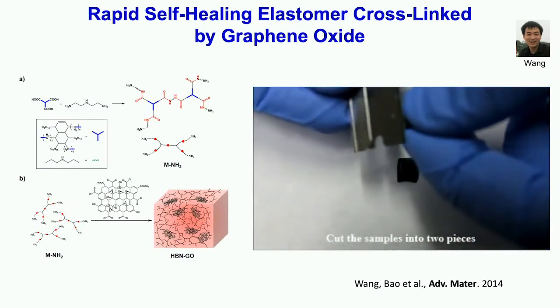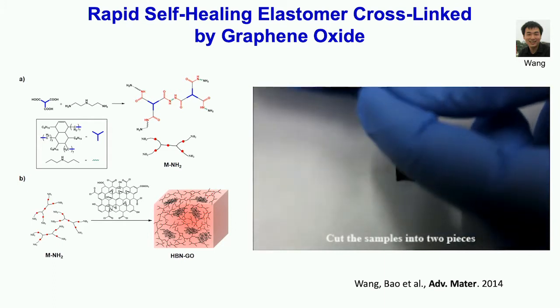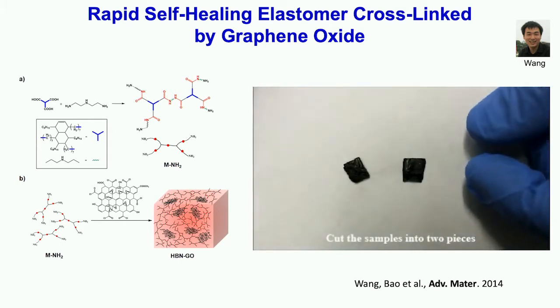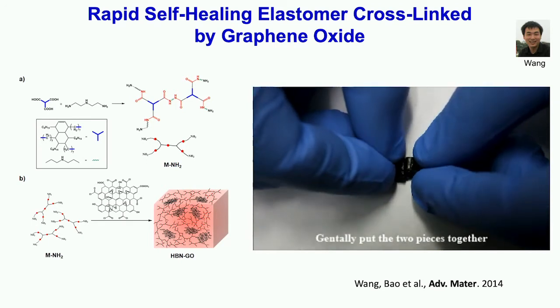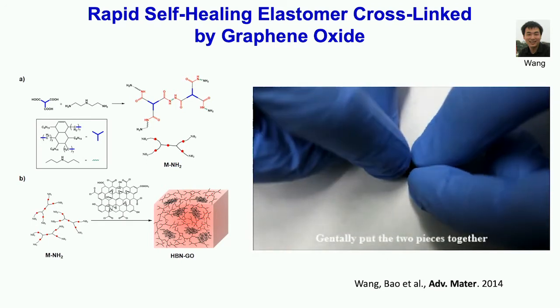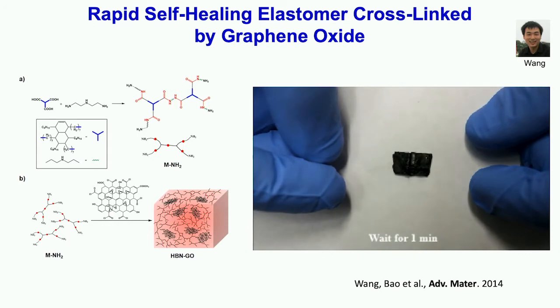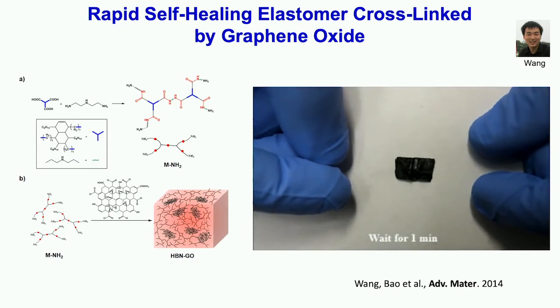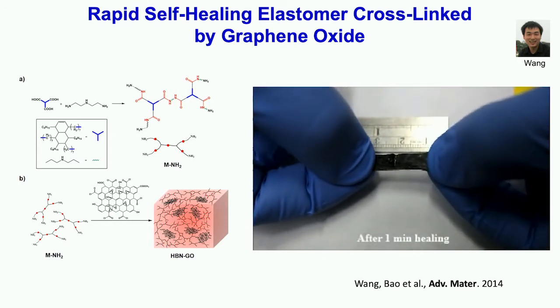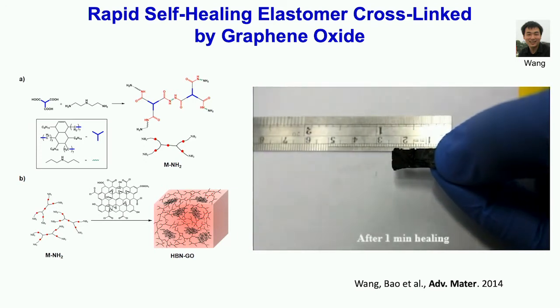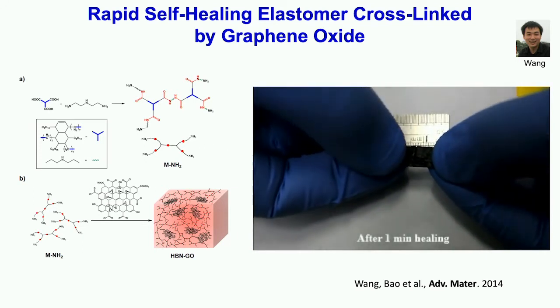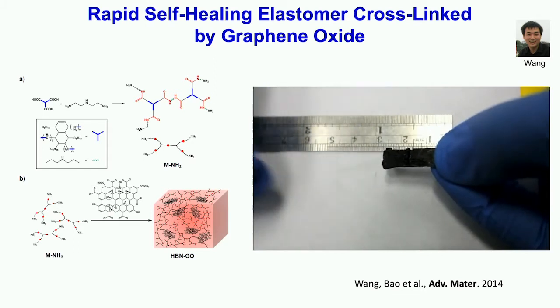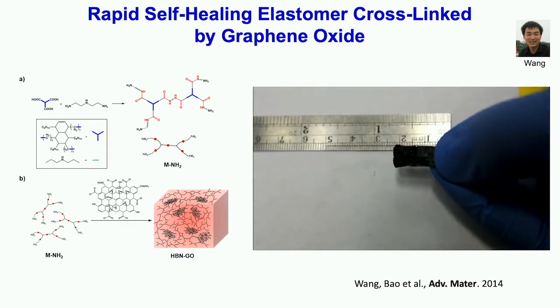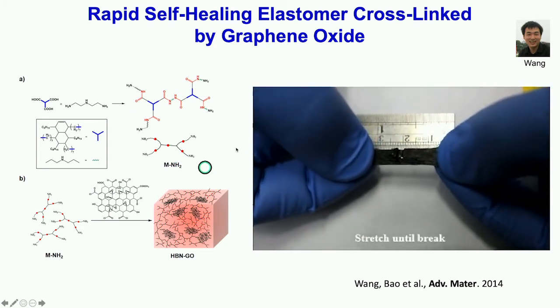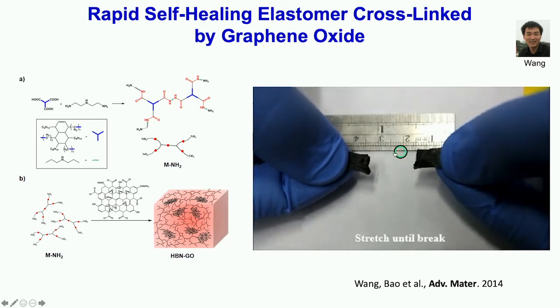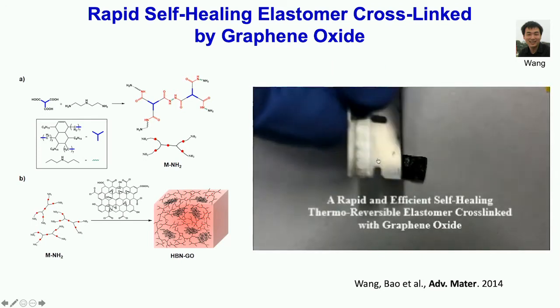So this shows the material being cut. And then when the two pieces are put together, the hydrogen bonding will start to recover, and that will recover the mechanical property of the material. So within a minute, we start to see the material has mostly recovered its mechanical property. But if you look closely, if there are defects, then it will start to show cracks.